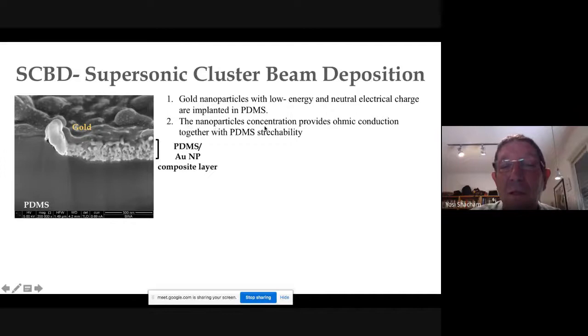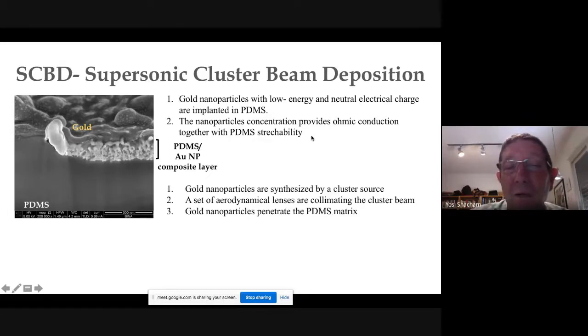The nanoparticles' concentration provides ohmic conduction together with PDMS stretchability. And actually, there's even a company now in Italy making and selling this technology. The gold nanoparticles are synthesized by a technology called cluster source, and a set of aerodynamical lenses are collimating the cluster beam, and the gold nanoparticles penetrate the PDMS matrix.